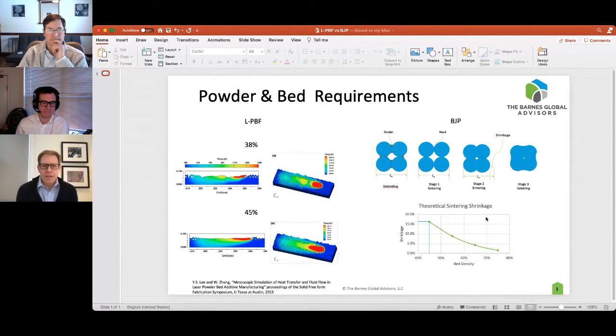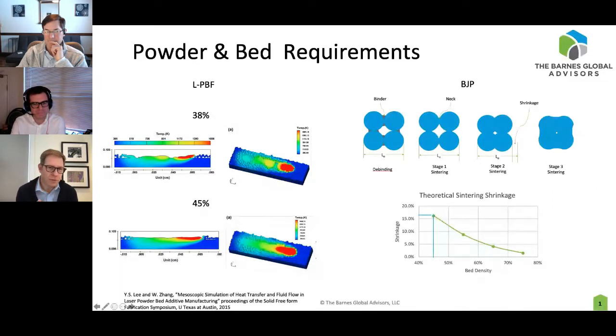Beautiful. So I look at this and the first thing that jumps out to me is the typical sintering diagram with the necking and powder particle interaction. Fundamentally, to me, this speaks to the principal difference between binder jetting and powder bed fusion, in that powder bed fusion is about weld pools in its basic sense, and so the need on the bed is very different than the need on the bed for binder jetting and ultimately sintering. That's the thing that I see in this.